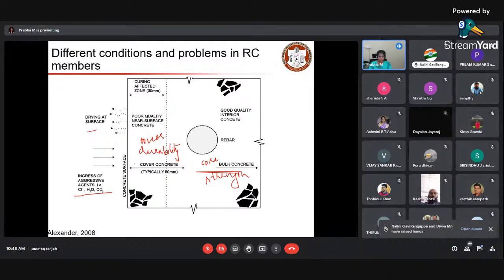So the idea is the covercrete. Here it is typically mentioned as cover concrete, and here it is mentioned as bulk concrete instead of core. All right. So the cover concrete we mostly give the least importance. We will not use good quality concrete, or we will not provide an adequate amount of cover depth. In some cases you might see that the rebar itself is visible because the concrete is not provided or placed to an adequate depth. Once the outer layer of the concrete, or even the mortar, peels off, you can barely see the rebar, right?